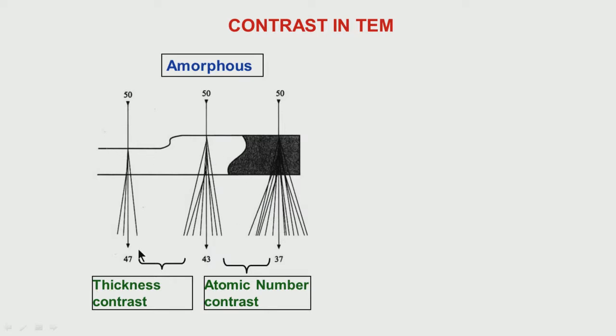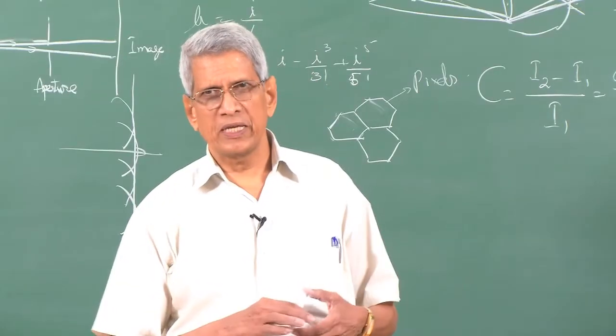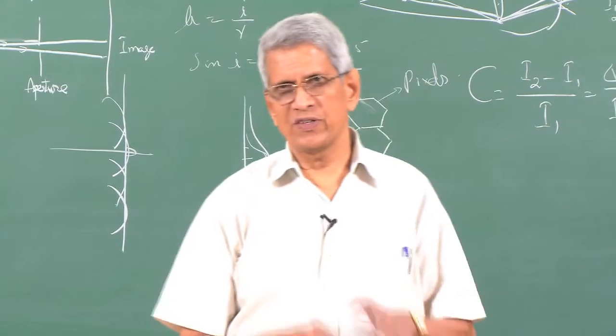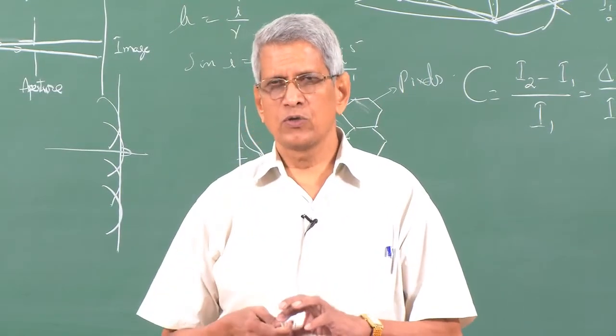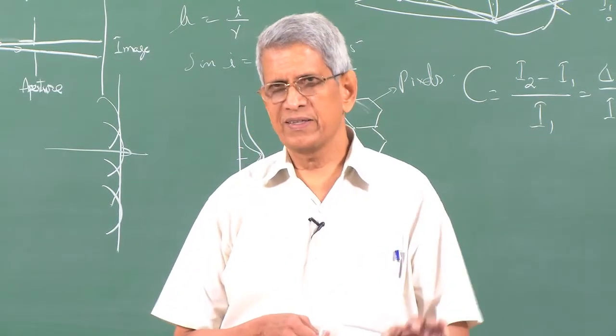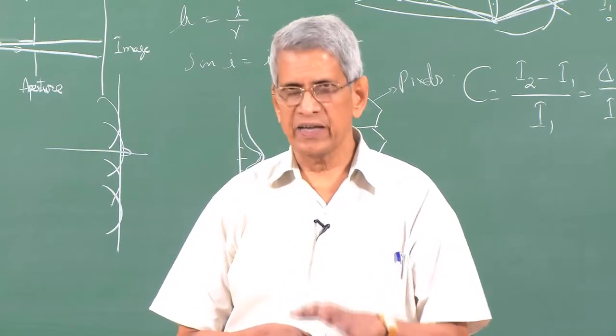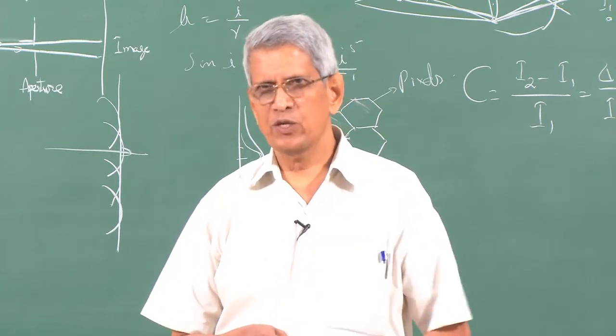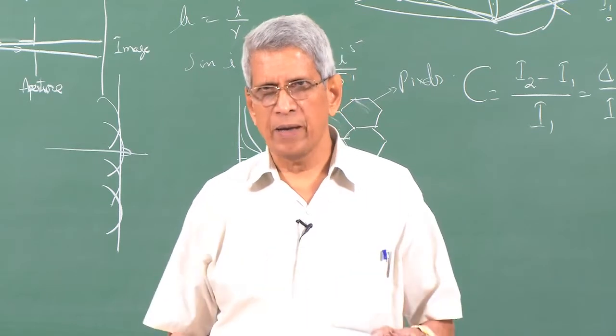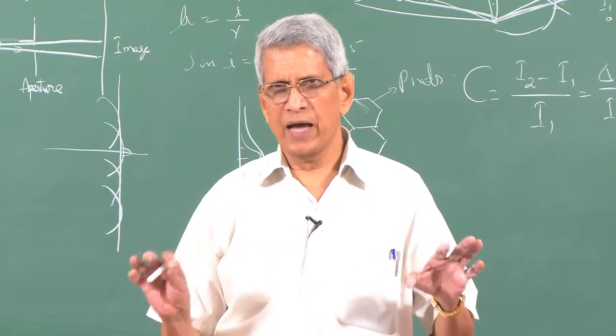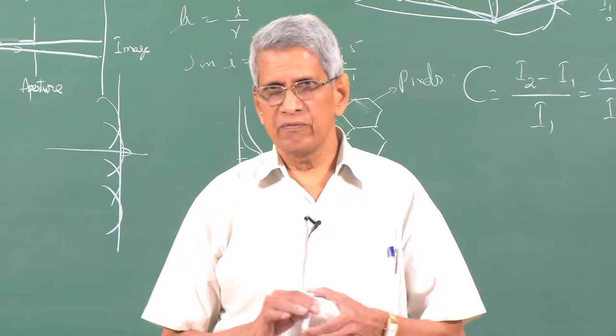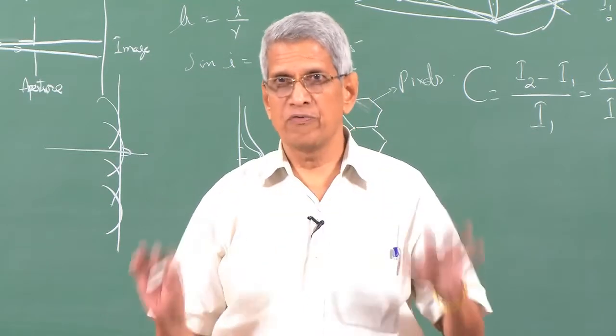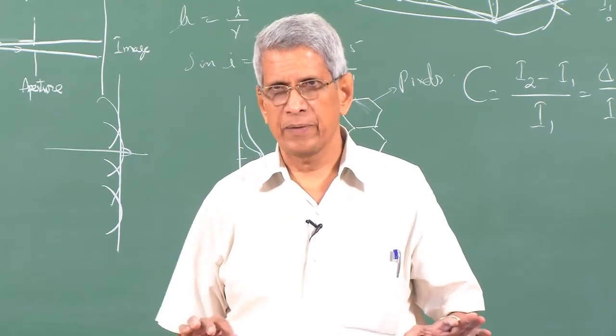So this contrast, we call it a thickness contrast. This contrast variation from here to here, we call it an atomic number contrast. In most materials, when we look at a microstructure, different phases have different composition. So both the thickness as well as the mass contrast will be simultaneously occurring in all the samples. This is what happens in a case where we have not considered that the sample is diffracting, because it's not a crystalline sample.